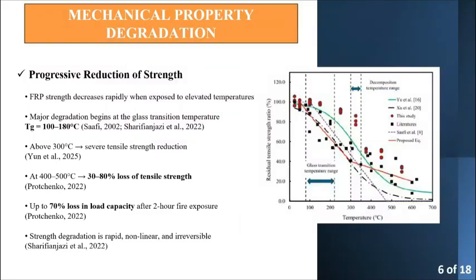Now let's move on to the mechanical property degradation. I will explain how the strength of FRP decreases when exposed to fire. FRP materials are very sensitive to high temperature because the main problem starts at the glass transition temperature, called Tg, which is between 100 and 180 degrees Celsius. At this temperature, the resin inside the FRP begins to soften. When the resin softens, the bond between the fibers and the matrix becomes weak, which causes a rapid reduction in tensile strength.